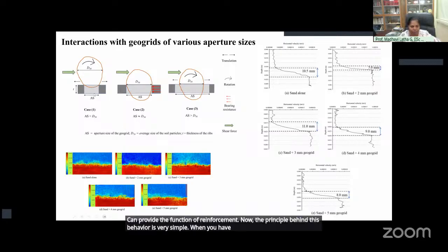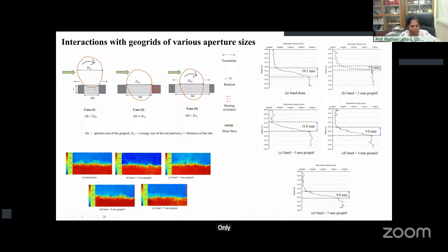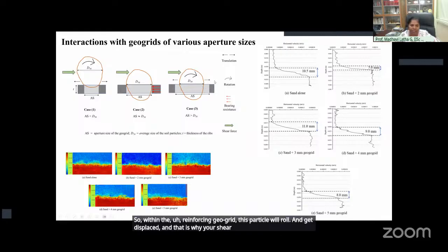Now, the principle behind this behavior is very simple. When you have aperture size smaller than the particle size, only a little bit of the sand gets interlocked with the aperture, and very easily this particle can be displaced in shear because of this low interlocking. Whereas when the aperture ratio is 1, your interlocking is perfect. The particle goes and sits inside the aperture, and you need very high shear stress to displace this kind of particle. Whereas if you have a higher aperture ratio, then the particle has a gap between the walls of the reinforcement. So within the reinforcing geogrid, this particle will roll and get displaced, and that is why the shear stress to displace this particle is also lower compared to the case where your aperture ratio is 1.